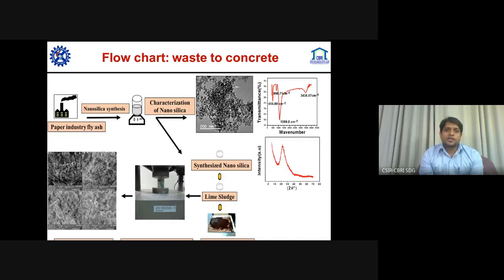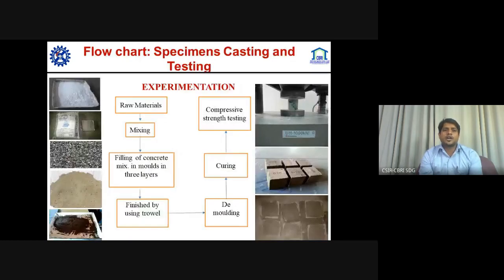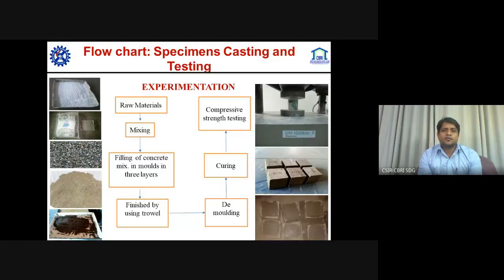So there is this flow chart of waste to concrete. The nanosilica was synthesized from the ash, and this synthesized nanosilica and lime sludge were utilized for the production of concrete, and all the testing was also done. The flow chart here for the concrete production shows the raw material and mixing, filling of the concrete mix in molds in 3 layers, finishing using trowels, demolding, curing, and further the compressive strength.